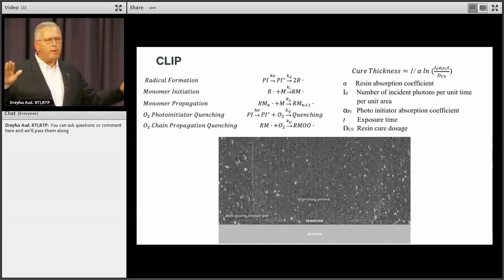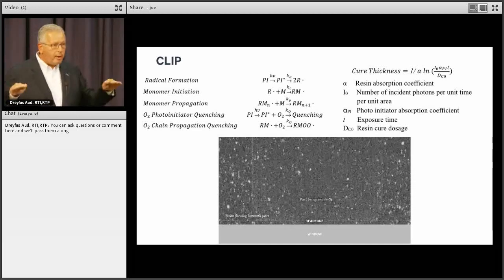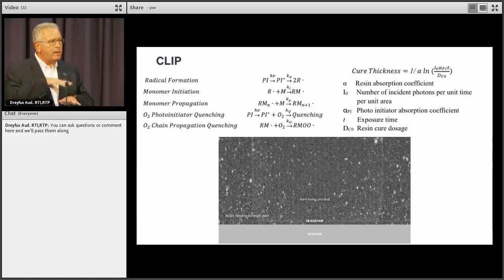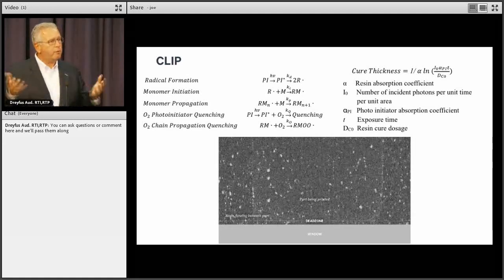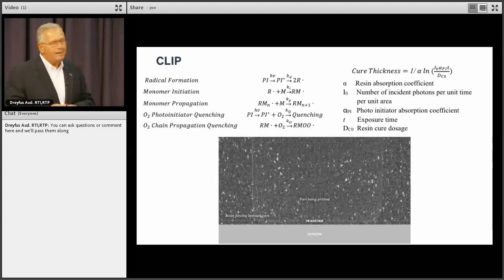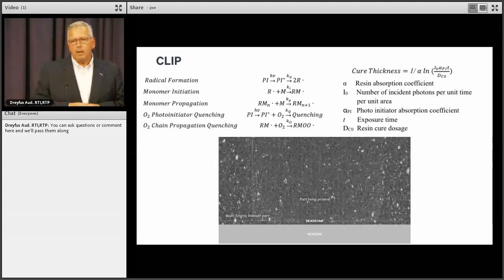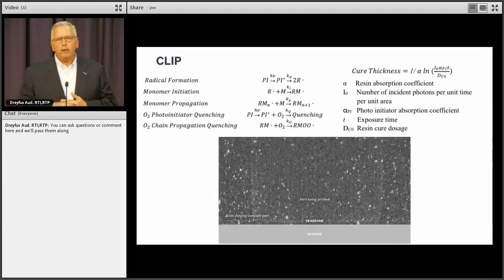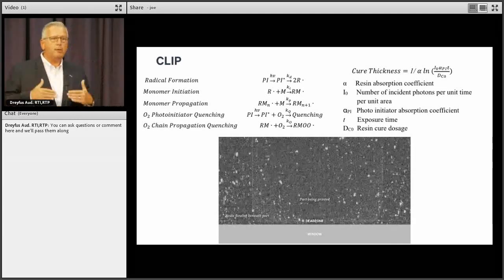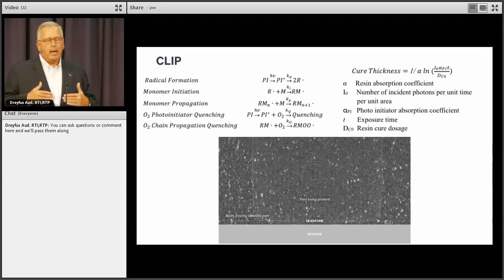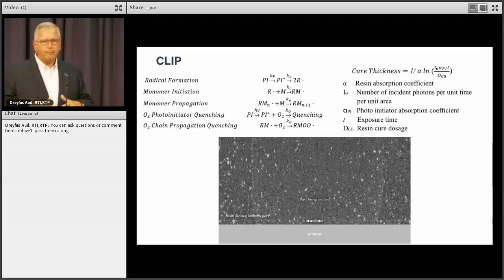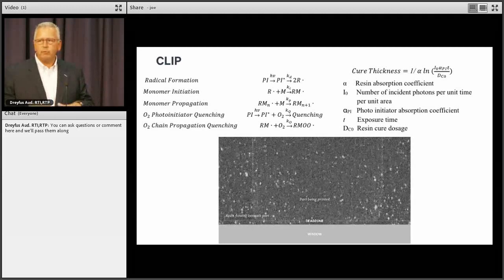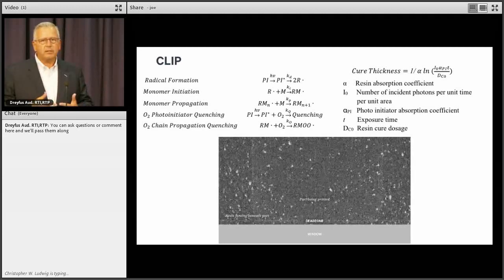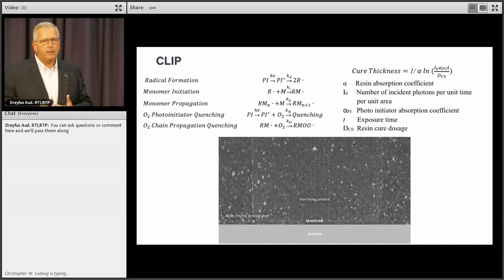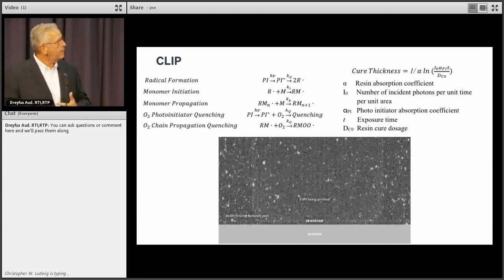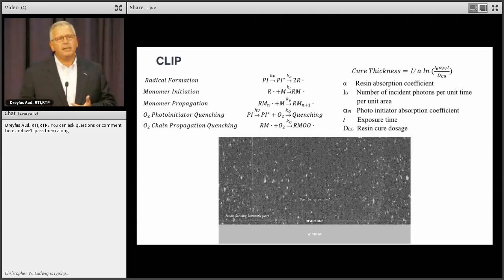And you see the resin flowing in underneath the part, right? Flowing in underneath the part, it gets consumed into the part and then it's pulled up. As you pull the part up, there are suction forces that bring the resin in underneath. If this were a standard window, impermeable to oxygen, right where the light's the most intense, we would be gluing the part right to the window. But instead, we have this sea of oxygen coming through the window as well that counteracts the photochemistry, that inhibits the polymerization chemistry, and that allows us to create what we call a dead zone, right?